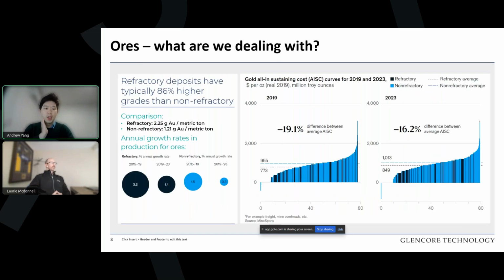When we then start to look at grades, we can also see in the surveys that refractory gold has a much higher grade than its non-refractory partner. In the past, it seems that our industry has focused on extracting from the non-refractory deposits because it's free milling, it's easier to send it through those conventional CIL circuits, leaving higher-grade refractory deposits in the ground. However, the survey is also showing that that trend is changing.